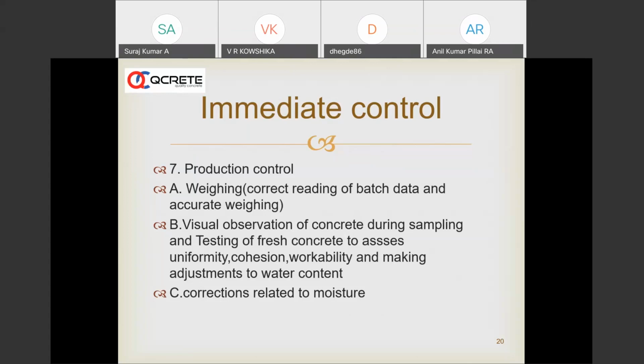We have seen over the last 15, 20 years, I have seen personally in big projects also, there is absolutely a lack of moisture control. In such cases, there will be huge variations in the slump as well as the strength. Both the fresh and the hardened properties will vary significantly, even if we keep all other things constant, which many times is not possible, due to uncontrolled moisture which creeps into many of the mixes.